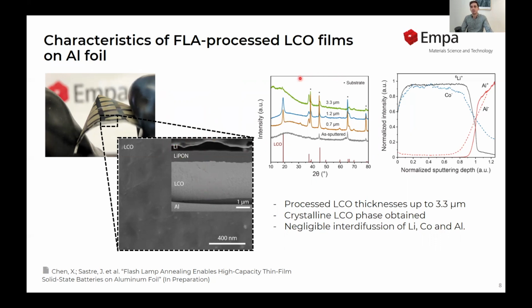Here is the XRD of the as-prepared LCO films and the ones after crystallization with FLA. The sputtered films show only peaks corresponding to the substrate, the aluminum foil, and when we apply the FLA, we observe the layered structure typical of LCO, lithium cobalt oxide. We investigated 3 different thicknesses, 0.7 micrometers, 1.2, and 3.3. In all 3, we observed the peaks corresponding to the LCO phase.